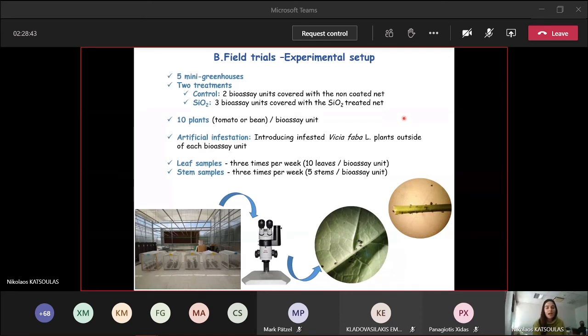In the field trials, we conducted three experiments. In the first experiment, we used tomato plants, while in the other two, we used bean plants, as they were considered more susceptible to aphid infestation. The infestation in this experiment was artificial, by introducing infested plants outside of each bioassay unit. After that, we expected the insects to walk on the net and enter the greenhouse in order to infest the healthy plants. Three times per week, we collected leaf and stem samples, and we measured the amount of insects on the leaves and the stems of the plants in the laboratory.